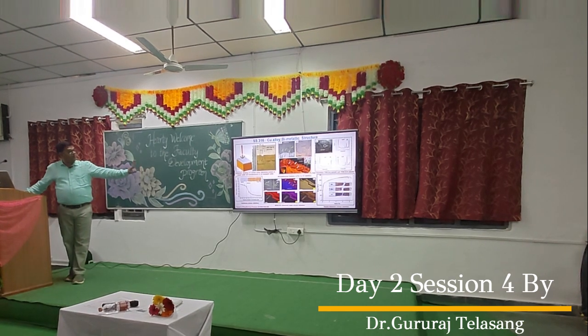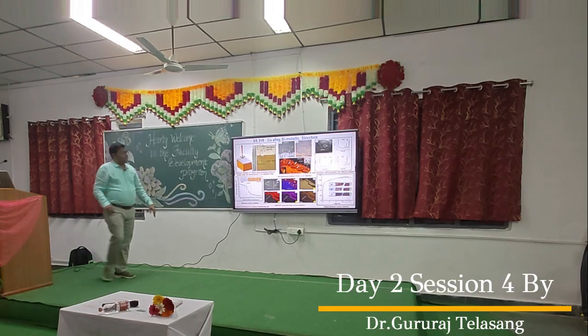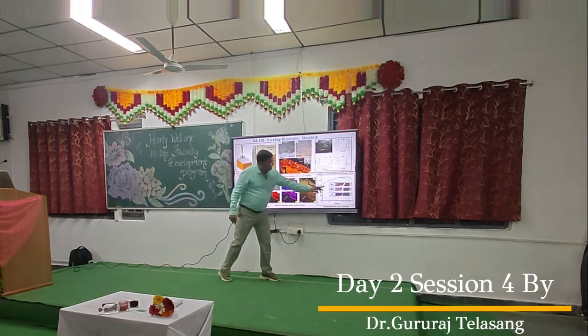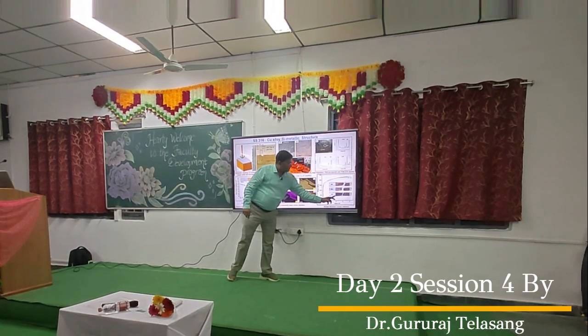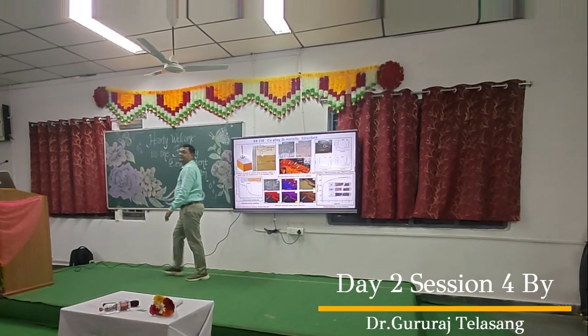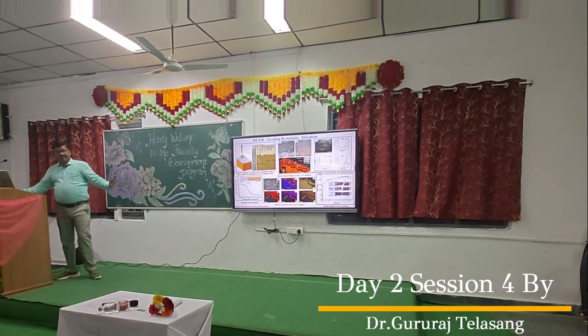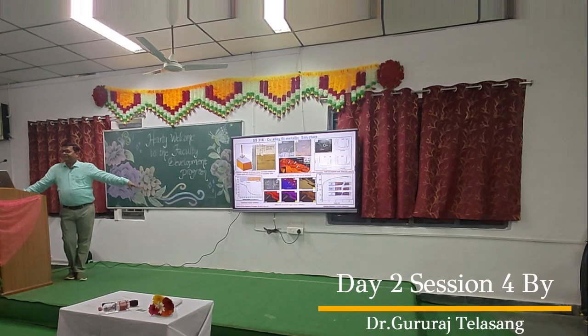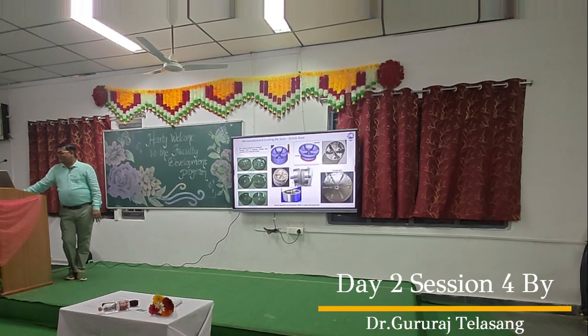And this is another work, copper to steel, very difficult to weld. We did additive manufacturing nicely. You can see it broke here on the copper side and the interface is still intact. This is accepted by a very prestigious journal. It's very difficult to publish in that. And it took almost 14 months and 5 iterations of review. Very difficult. But somehow we managed.